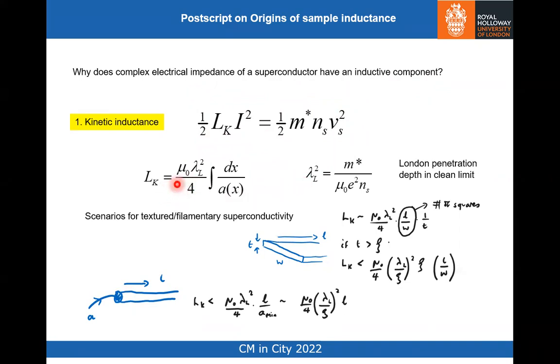It depends on the London penetration depth times some geometrical factor. That geometrical factor is the integral over the length of some channel of the inverse area of the channel. So you can consider 1D filaments or 2D filaments, and then they're going to give you an upper bound on the kinetic inductance, which depends on some combination of the London penetration depth and the coherence length.